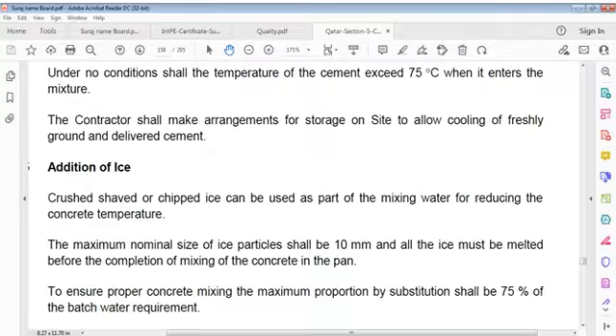Addition of ice. Crushed, shaved or chipped ice can be used as part of mixing water for reducing concrete temperature. Maximum nominal size of ice particles shall be 10 mm, and all ice must be melted before completion of mixing of concrete in pan.